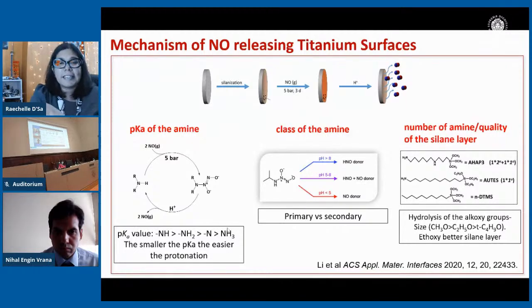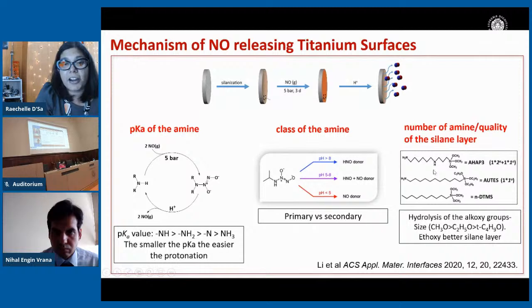So what we thought was going to be quite an easy study initially actually turned out to be quite complicated. And we did a lot of mechanistic studies, which I won't go through today, but it's just recently published in ACS Applied Materials and Interfaces this year, into how the pKa, the class of the amine, and the quality and the type of the silane layer actually affects the rate of release of nitric oxide from these surfaces. So it's not a simple, we can do one thing and we get one result. It has to be varied on all these 3 different conditions that have to play into one another to be able to get a controlled nitric oxide release.